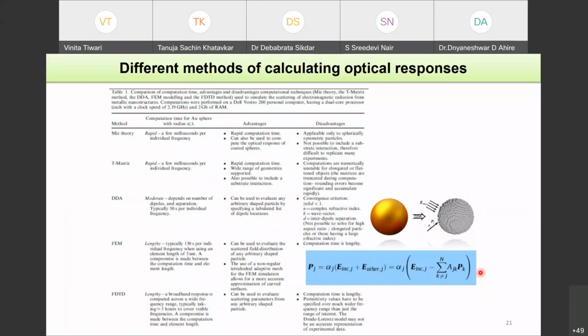Another important aspect is the different numerical methods available for computing the optical responses of nanoantennas. One very standard method is called Mie theory, which was solved by Gustav Mie in 1908. It's a very standard theory that allows you to calculate the scattering and absorption cross-section for spherical nanoparticles. But this doesn't apply to nanoparticles of different shape, or even to nanoparticles which are close to a substrate.